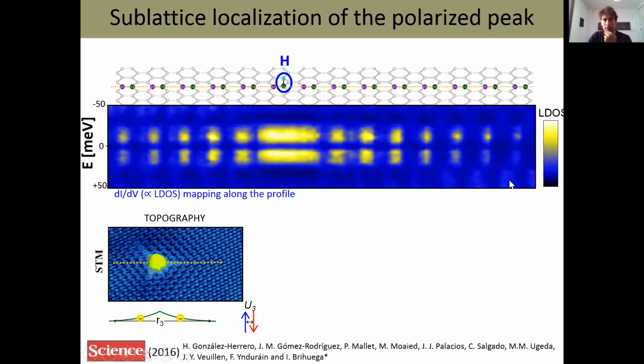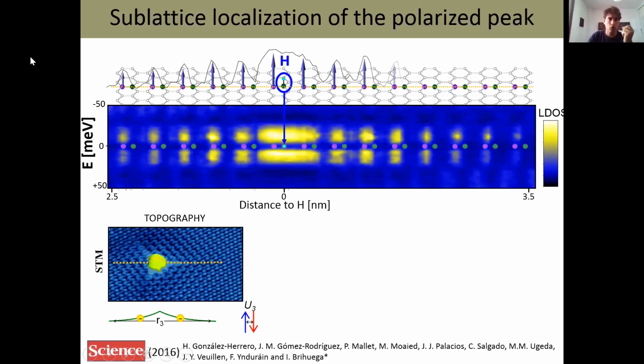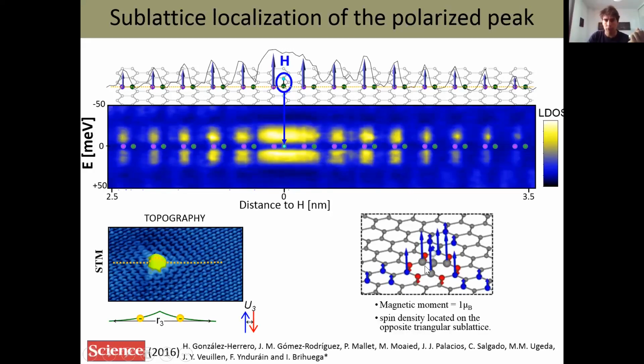Now the horizontal axis is distance from the hydrogen atom, and the vertical axis is energy, and the color code is for the density of states. Bright yellow means high density of states, dark blue is low density of states. Just to guide the eye, I will put the position where the hydrogen atom sits. Here is where the hydrogen atom is, and here in purple and green, we have the position of the carbon atoms. And what we can see is that these bright yellow features, which are associated with the two peaks, with the magnetic moments, are located at the position of the purple atoms. So we can now really see where the magnetic moment is sitting, and if the hydrogen atom is absorbed on the green sublattice, we see that a magnetic moment develops on the purple sublattice. And this is exactly what was predicted by theory.